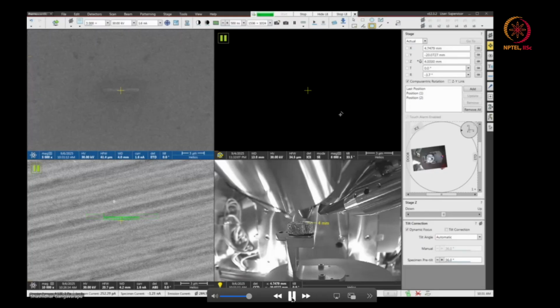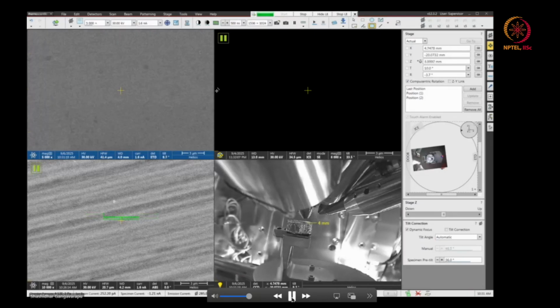The next step is to do eucentric. So first, what is eucentric? Now you can see that once I tilted my sample, my feature moved from the center to the bottom. So using the Z height stage movement, I increase the Z and bring my sample to the center. This process is called eucentric. Eucentric is basically, at a particular objective lens current value and a particular Z position, the region of interest will not move during tilting.